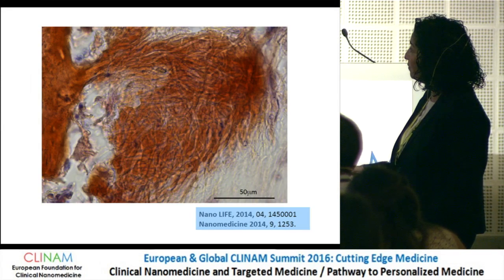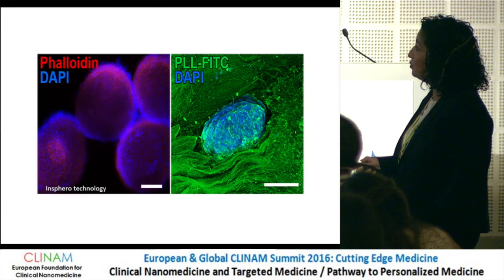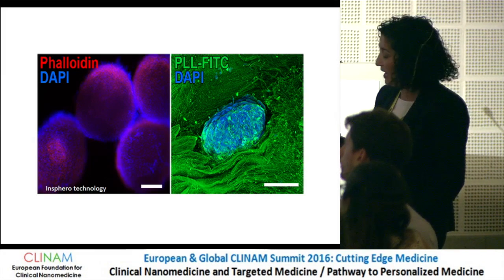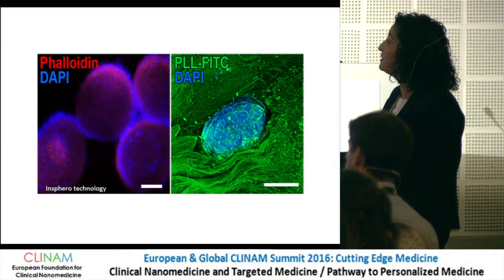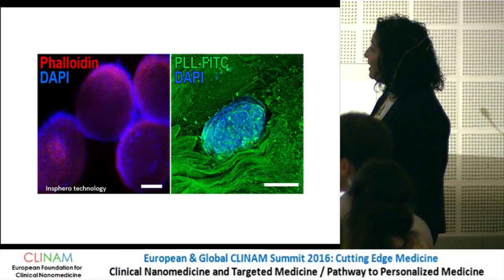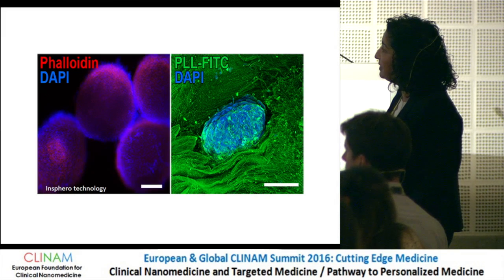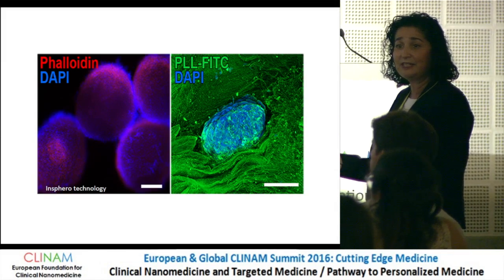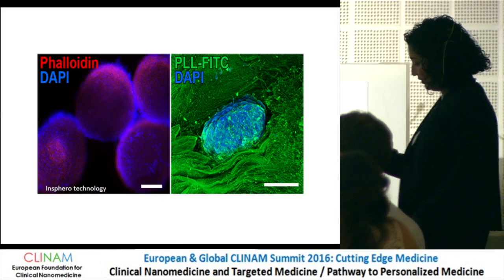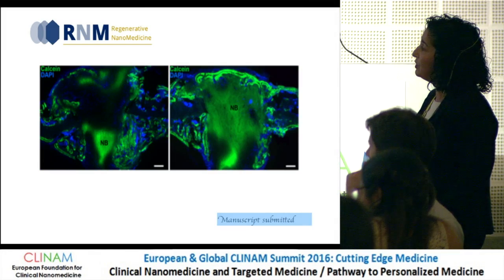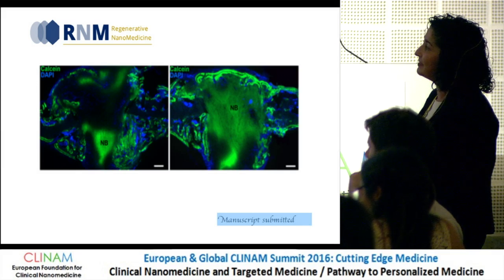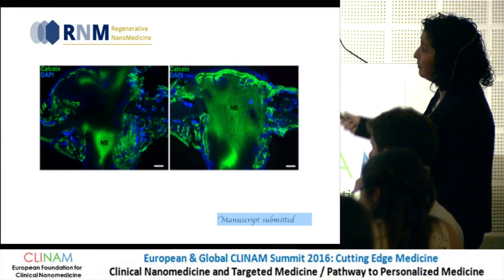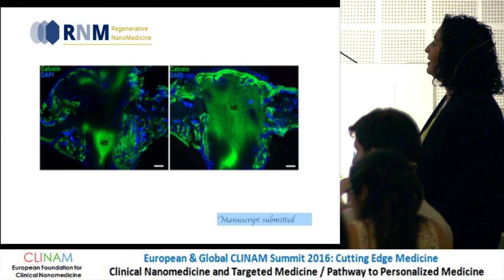You can see here the regeneration of bone in contact with host bone in vivo. We also used micro tissues — the spheroid technology — to further increase the speed of bone regeneration. We have a double 3D system: the spheroids are the first 3D environment, and the second is the 3D nanofibrous membrane. This double 3D system increases the speed of bone regeneration, validated in vivo comparing single cells versus spheroids with active nanoreservoirs of BMP2, showing more bone regeneration in shorter time.